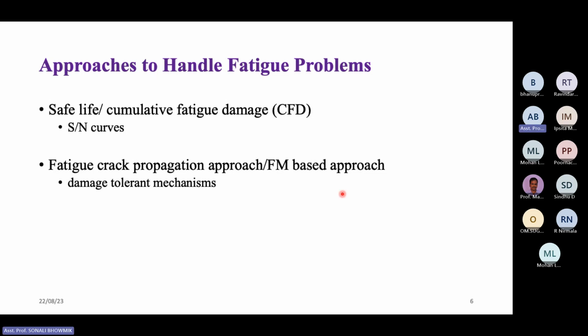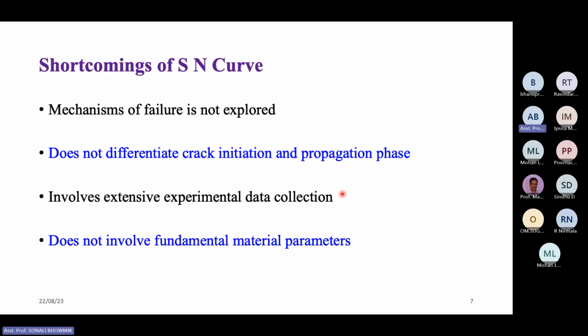For concrete, there are many other approaches, like the fracture mechanics based fatigue crack propagation approach, through which one can predict the fatigue life. The S-N curve approach is not valid for concrete structures because it does not fully include the concrete failure mechanism, and does not differentiate the crack initiation and propagation phases. Concrete is a bit more complicated than alloy, because in concrete there is a fracture process zone, as I have explained, which is non-linear in nature. So it cannot accurately address the problem. It involves extensive experimental data collection and does not involve fundamental material parameters.